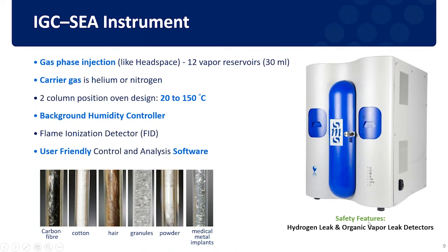And we do have some safety features of the instrument that we equipped it with, the hydrogen and organic vapor leak detector that allow you to detect the concentration of the organic vapor surrounding the system, and shut down if there is any safety reason. And here are some of the samples we packed before with our instrument. We ran some fiber sample or some powder sample, and we can also run some porous material as well, like active carbon or some MOF material.